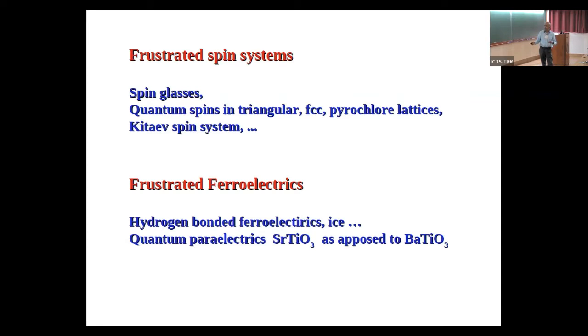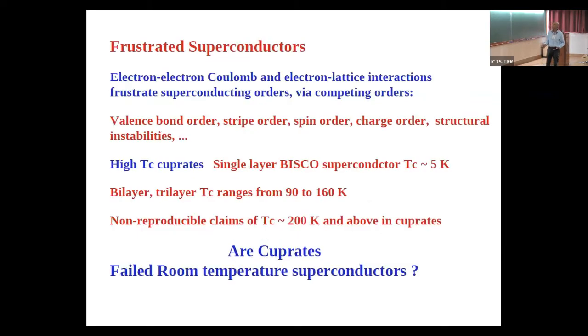Then even perovskites like strontium titanate, cubic perovskite, and barium titanate are very similar in terms of structure, and barium is heavier than strontium. Strontium titanate is a paraelectric, it never becomes a ferroelectric, whereas barium titanate is a good ferroelectric. This is due to quantum fluctuation, which never allows even ferroelectricity to form, so it remains a quantum paraelectric. So these are all well known.